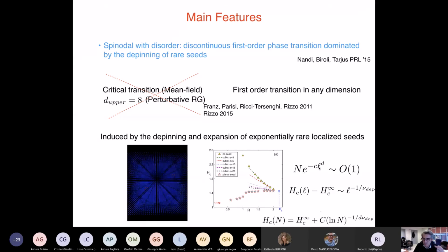And then, it's known that if you have a seed of size L, just using the critical behavior at the depinning transition, the critical value at which the seed of size L can depin will be larger than the one for an infinite seed, by a factor which is L to the exponent -1 divided by nu depinning, where nu is a critical exponent of the depinning transition. So if you put these two things together, you will find that in a system of size n, you can have some seed of some size, but not seeds of any size, because these are too improbable.